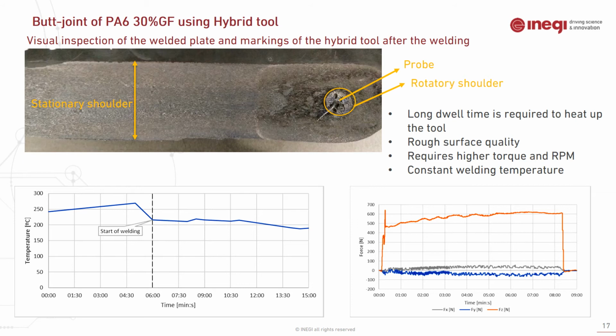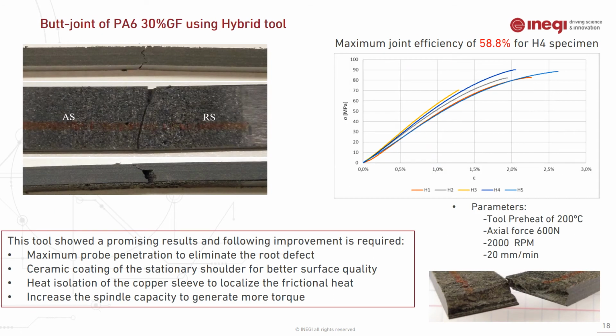As you can see on the temperature and time graph, the temperature was much more stable using this tool due to being a steel material, and also on the right you can see the actual forces during the welding. Despite the fact that the surface quality was poor when compared to the PEEK tool, the strength of the welded specimen was higher.